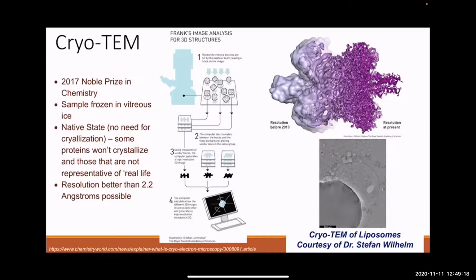So the idea is you have to freeze, and that requires its own state-of-the-art equipment because you don't just put it into the freezer and take it out 4 hours later and look at that ice. You have to freeze it very, very quickly because you want amorphous ice. If you don't freeze it very quickly, it'll crystallize. But the idea behind it is you can take something like a protein structure in water and freeze it, and then put that in the TEM and keep it cold. So you have to have a stage in the TEM that keeps it at liquid nitrogen temperatures.